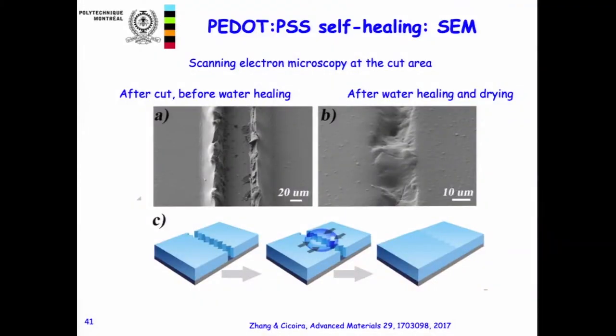Then, OK, we went to have a look at what happens to the healed part. And you see, actually, that this is the cut just after you pass with your blade. And this is after you put water. So actually, there is material where there was not material after you cut. So it's a real healing process. You restore your film after the cut.